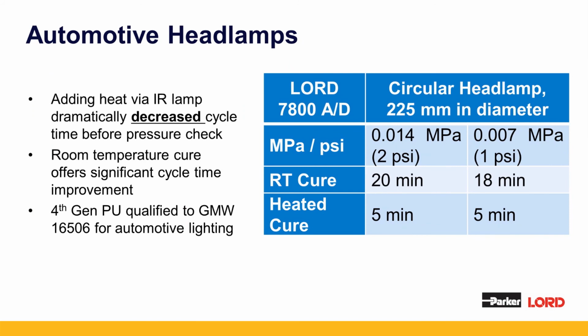With this example, I'd like to highlight, in this case, just a circular headlamp where we did testing on it. We did the traditional pressure check of between 1 and 2 psi. Some manufacturers use 1.5. In the first example, we did a room temperature cure. This product has a 4 to 7 minute open time, the 7800 AD, and we're able to achieve those positive pressure checks in as little as 18 minutes. Interestingly enough, when we add an IR lamp to it, we can dramatically decrease the cycle time before that pressure check. In this case, we were able to achieve about 5 minutes before we did the 1 to 2 psi check.